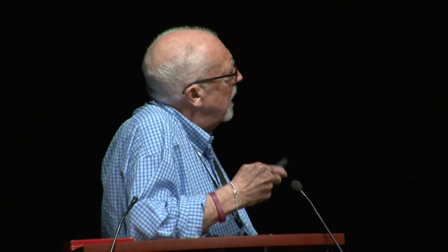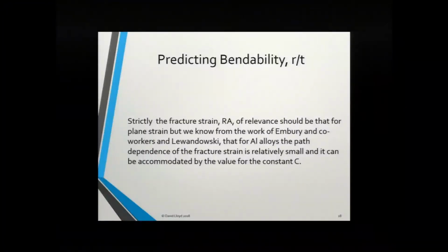If you don't have a moving axis, this equation still applies, but C is now down, they suggested 50. The experiments that we've done on high strength 2000 series alloys suggest that it's closer to 40. But anyway, that equation can be used, and we've shown a variety of data plots of this in the literature over the years. Strictly, the fracture strain should be measured in plane strain, of course, because that's our deformation mode. But Embury and the group down there, and also Lewandowski and others, have shown that for aluminum alloys of the types we're looking at, the path dependence of the fracture strain is relatively small when you move from measuring it at the tensile path as against the plane strain path.